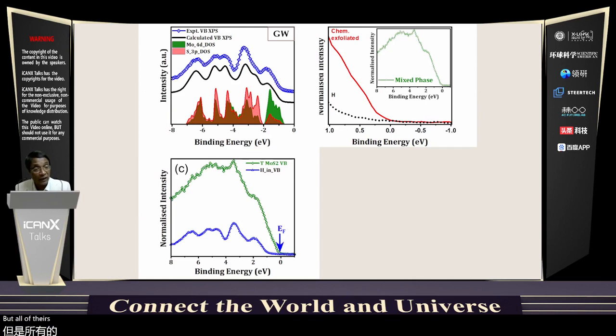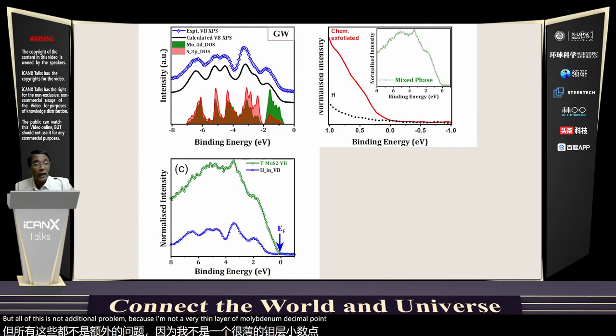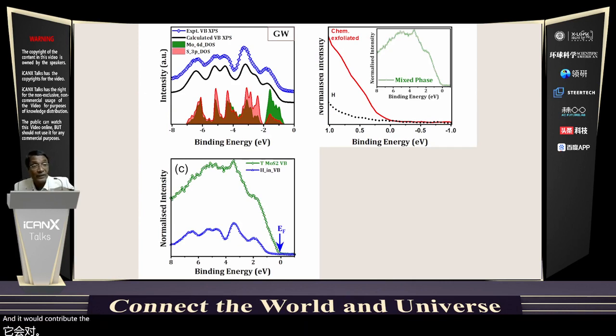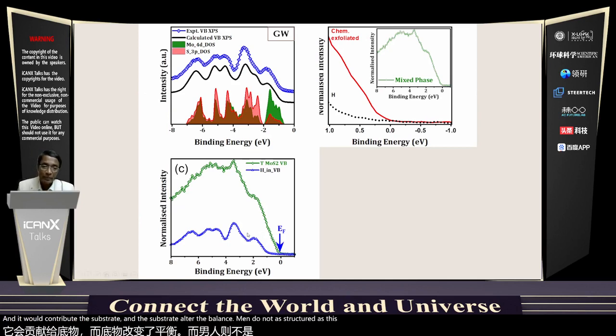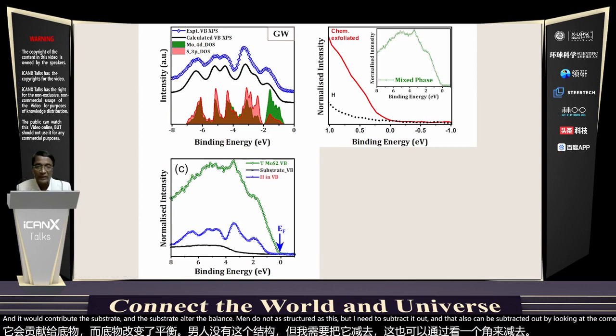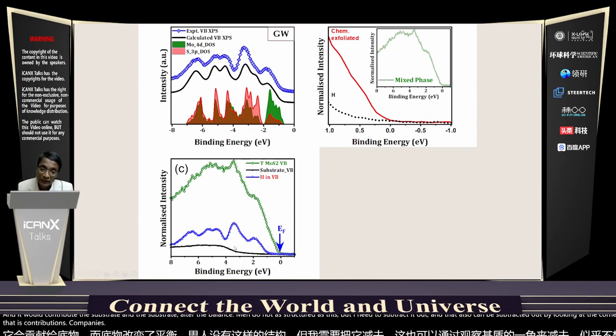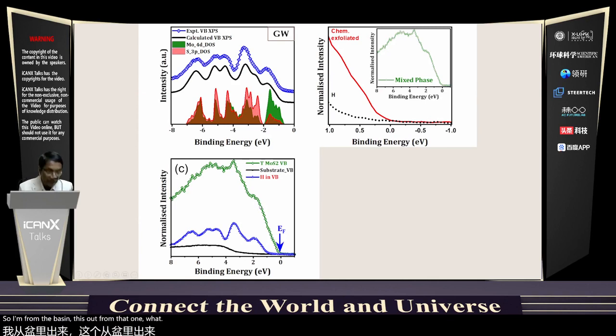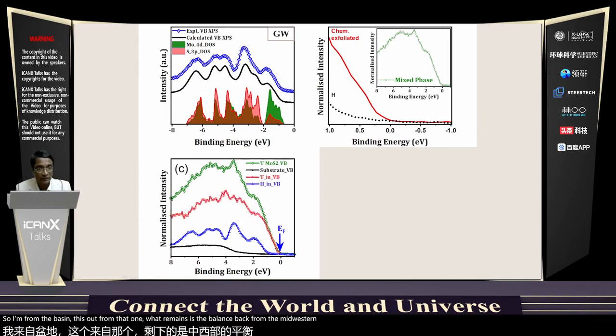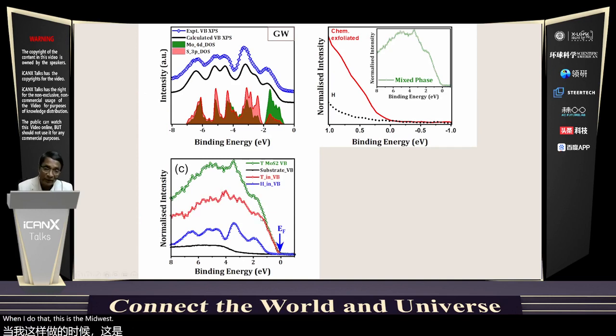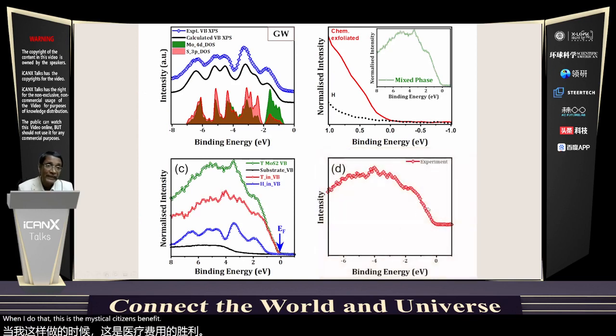But there is also an additional problem, because I'm looking at a very thin layer of molybdenum disulfide, and it would contribute the substrate. The substrate also has a valence band, though not as structured as this, but I need to subtract that out. That also can be subtracted out by looking at the core level of the substrate seen through the molybdenum sulfide, and that contribution comes like this. So I'll subtract this and this out from that one. What remains is the valence band from the metastable state. When I do that, this is the metastable state valence band spectrum. And then that is the one that I compare with the calculation.